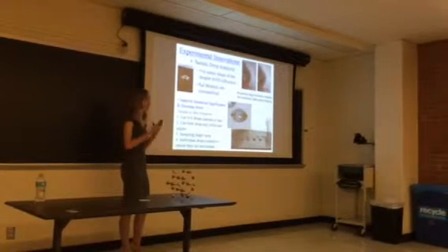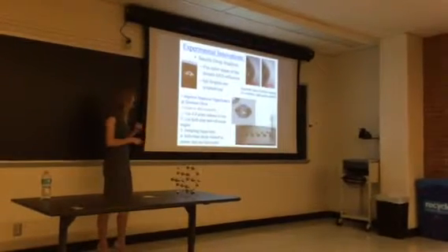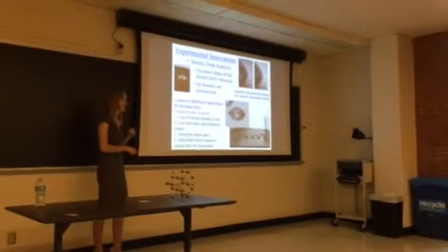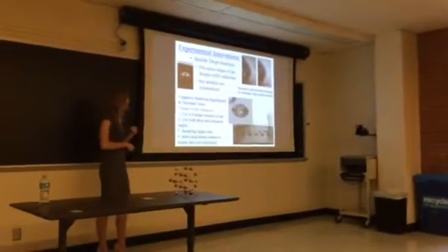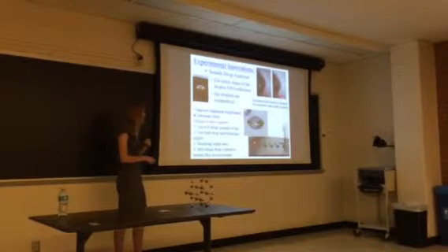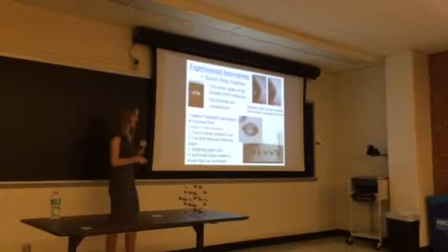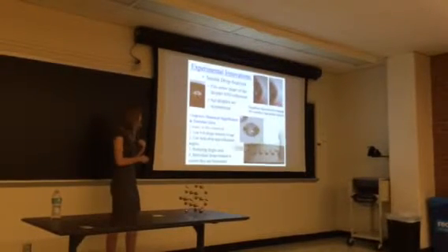The 6 microliter droplets are very important, as larger ones will be affected by gravity. Also, again, we have 4 contact angles per droplet, and we use many droplets on our surface in order to improve statistical significance and test a larger portion of our area. Also, we made sure to rotate drops that were warped through our camera, and to make sure that they're horizontal so that our ellipse fit would be accurate.